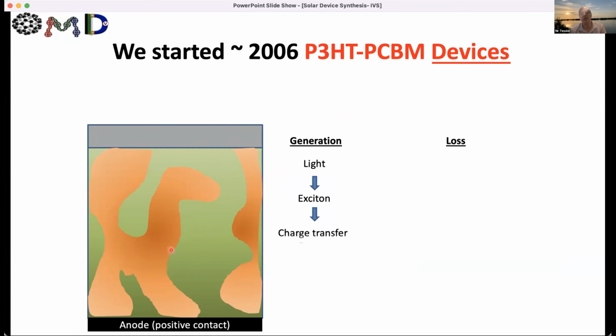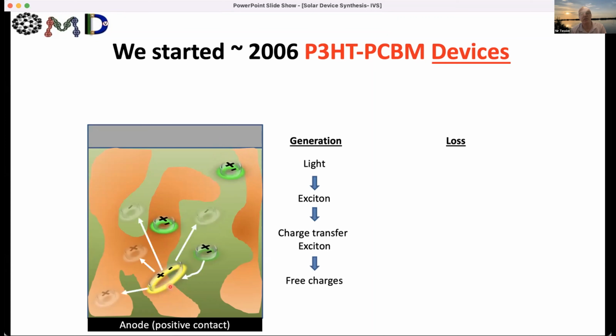And when we shine light into it, then what we have is generated excitons. These excitons would diffuse to the interface, and they will create charge transfer excitons. And hopefully these would split into charges, which we call free charges, that would then drift and diffuse to the electrodes to produce current. This is the ideal case, but ideality is only in the textbooks sometimes.